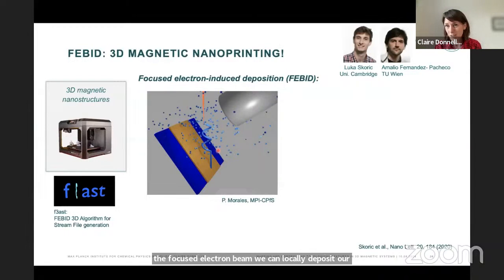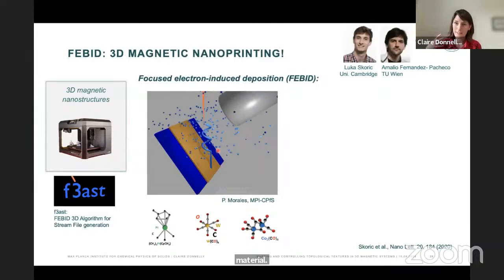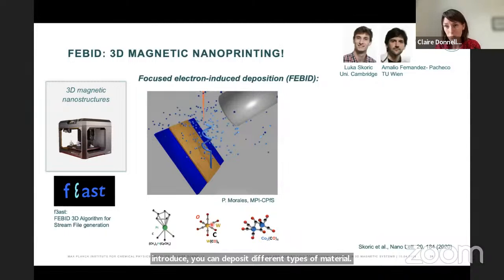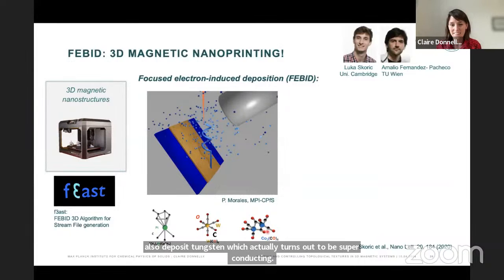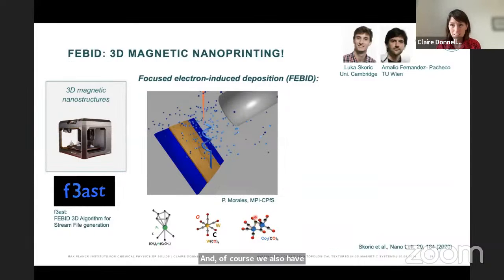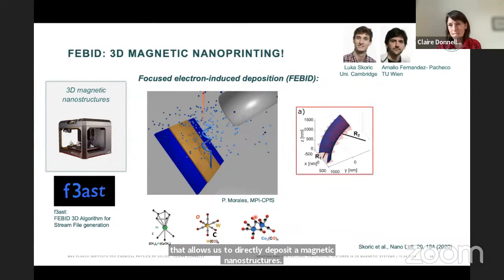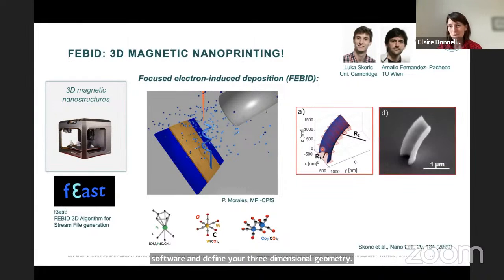Depending on the gas that you introduce, you can deposit different types of material. For example, the standard one is platinum. We can also deposit tungsten, which turns out to be superconducting. And of course, we also have a cobalt precursor that allows us to directly deposit magnetic nanostructures. The typical idea is that you go to a CAD software, define your three-dimensional geometry, feed it into Amalio's program, and in the end, go to your microscope and pattern a three-dimensional geometry of your choosing.